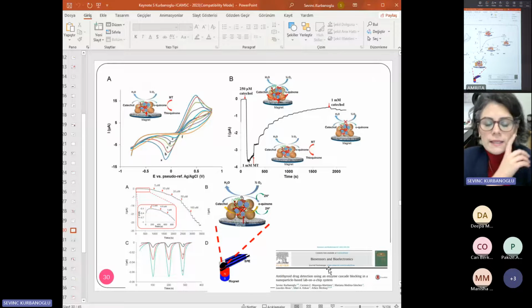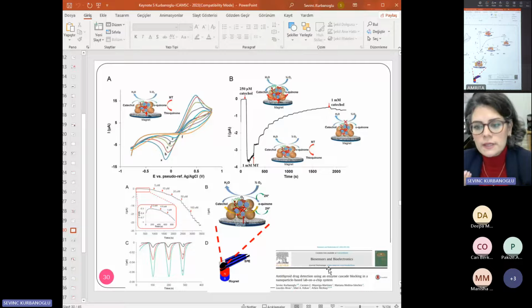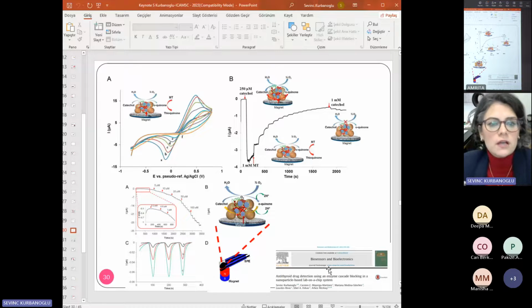So for this idea, first we try to find a stable system that we can also use for inhibition studies. We tried to find a very good nanobiosensor, actually. For that, we use magnetic nanoparticles. Under the screen printed electrode, we put a magnet, and on the surface of the screen printed electrode, we put magnetic nanoparticles, onto which we immobilize the tyrosinase enzyme, and we try to follow first the catechol and orthoquinone conversion, and we try to optimize the first biosensing responses. Again, we use the amperometric method, and we had a good linear range.